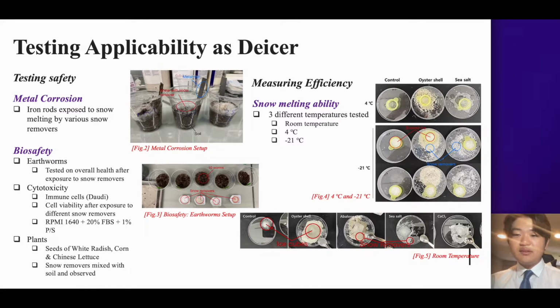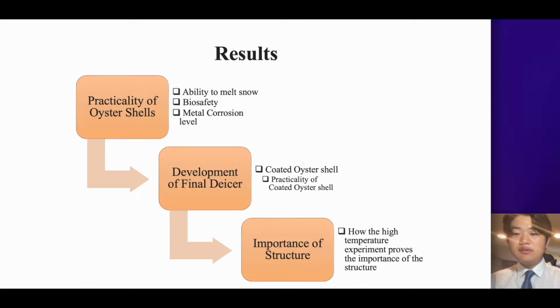For testing plant safety, de-icers were mixed in the soil with the plant growing, and the plant was cultivated in soil under the same conditions, apart from using different de-icers. Over time, the occurrence of problems in plant growth was observed. As for the analysis of ice melting rate, ice cubes were used at room temperature, and the weight of each ice cube was measured before and after exposure to different de-icers. In the case of 4 degrees Celsius and negative 21 degrees Celsius, the weight of melted ice was measured using ice powder. Now, let me present the overview of the results of the above analyses.